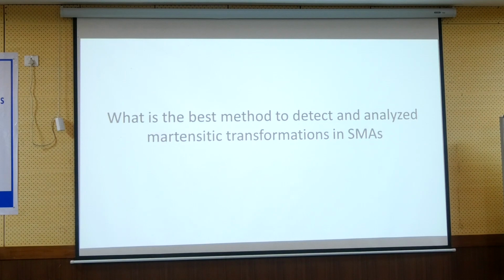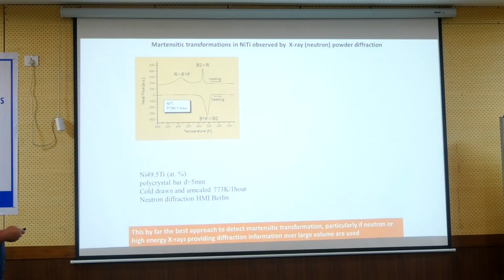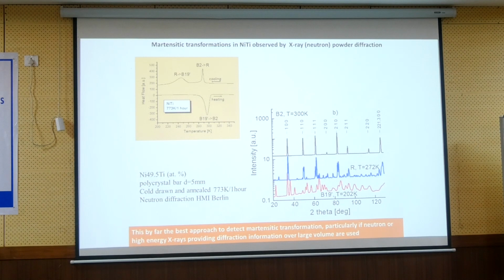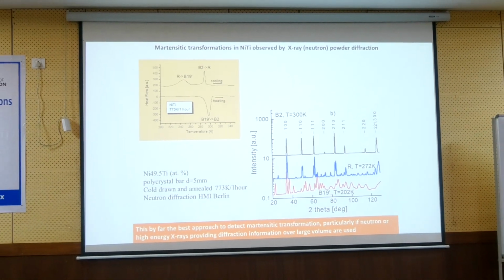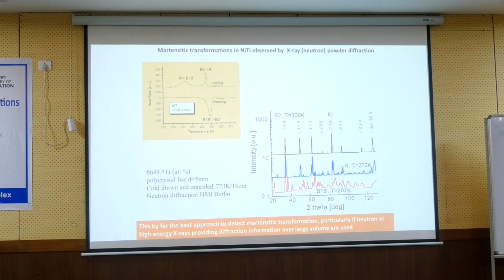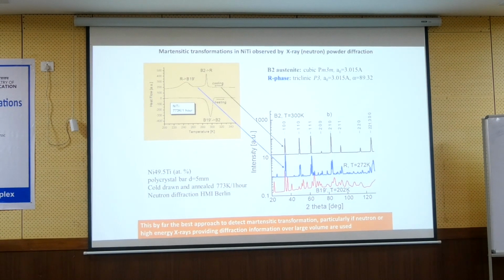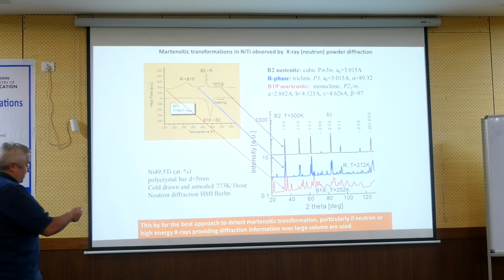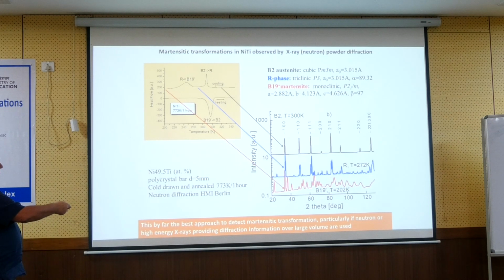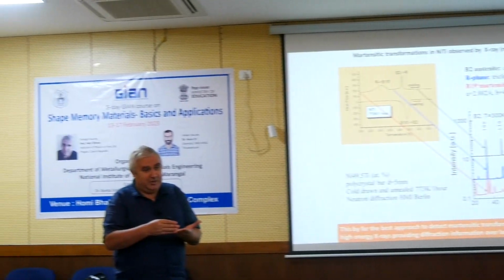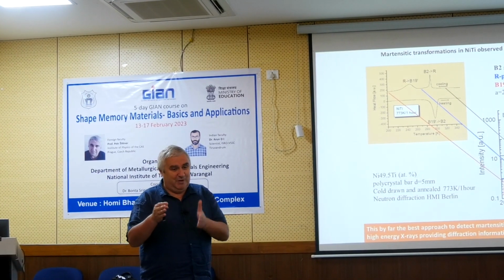You know? So, well, my answer to this question is that the best way to characterize whether I have martensitic transformation in the alloy is X-ray diffraction. Why? Because it tells you a lot of things together. It tells you the structure of phases you have. So if you polish your sample and make measurements with lab X-rays, the measurement takes time, so you have to make a few measurements.